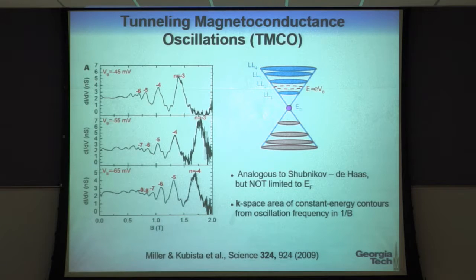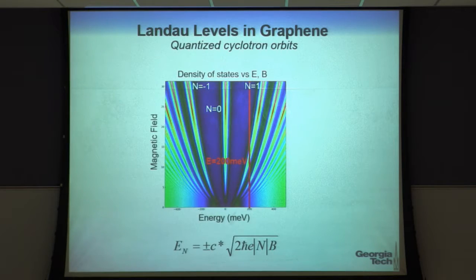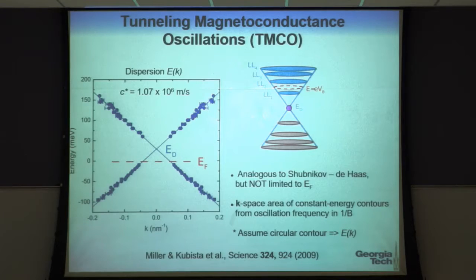We can take a different cut, obviously. It's not that obvious. Experimentally, there are issues. This experiment where I sweep the magnetic field has to be done in closed loop so that the tip is always tunneling to the surface, because when you change the magnetic field, things move a bit. And you don't want to crash the tip into the surface. So this cut, though, actually allows you to get information at a lower magnetic field than was necessary for getting those discrete peaks that I showed you.